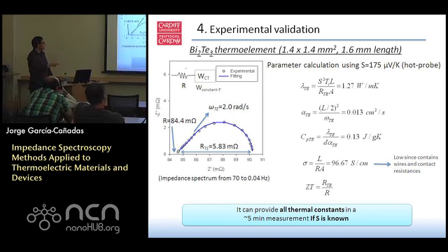And then of course you can track your ZT, which is the ratio between the 2 resistances in case you remove the contribution from wires and contacts. And usually the experiment is more or less quick, it takes a few minutes, 5-10 minutes, no more.